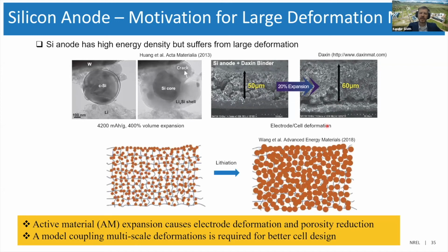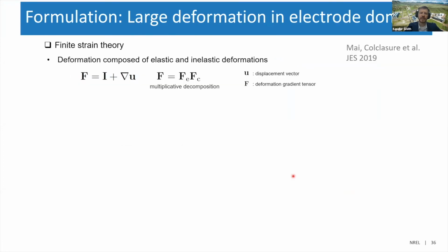And so, just kind of a cartoon of this is that these small particles get much larger, and that causes the thickening of the electrode as well. Also, the material seems to become more porous over time. Both turns from a crystalline phase, if it started out there, to amorphous, and then also becomes more porous. So we'd like to guide cell design with this model.